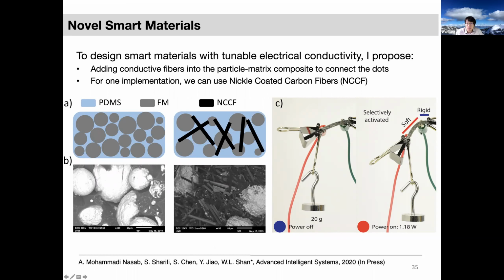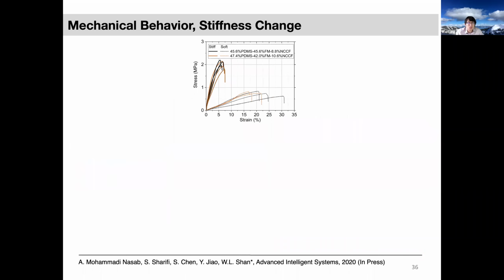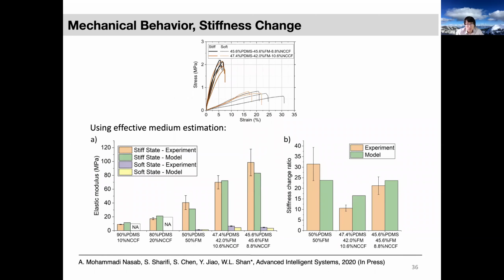So I have one beam here, I can run current through this portion, and we can activate this portion, while this portion is still not activated. We actually did a calculation of this smart composite, and this is a stress strain plot. Here we used effective medium estimation to characterize the stiffness change. As you can see, we are able to achieve roughly 20 times stiffness change for this composite when we vary the volume fraction this way.